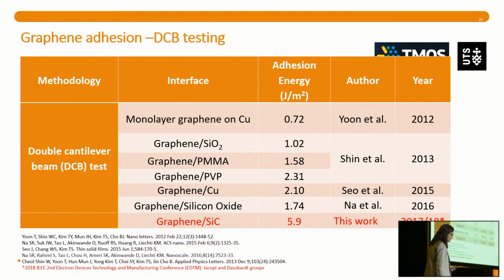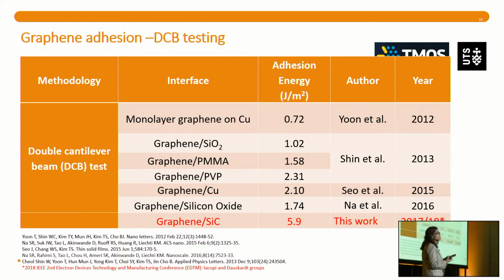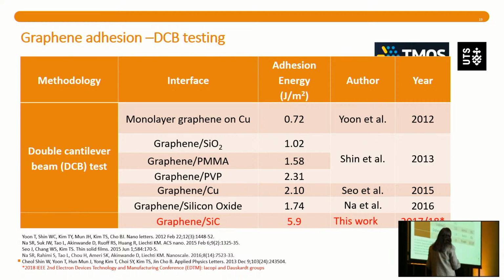Coming back to adhesion, graphene is a 2D material. So the ideal 2D material would have no bonding in the Z direction, and would only interact by van der Waals forces. Van der Waals forces in engineering terms correspond to more or less this type of adhesion energy, in joules per meter square, so roughly between 1 and 2. If this number doesn't tell you much, just remember that graphene can be exfoliated, right? So it means that you can easily take it away from the substrate underneath and place it somewhere else. You have some work to do with the modulus, to bend it, but that's more or less the value.